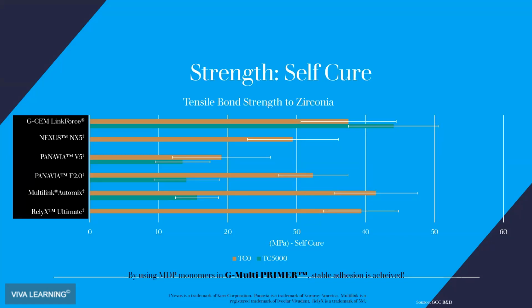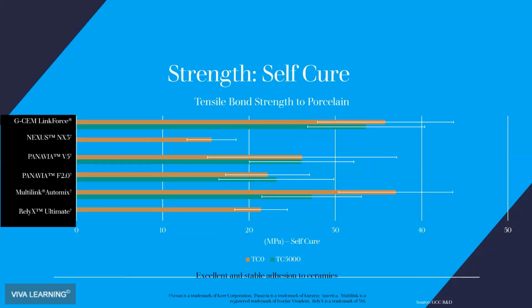We see that when we compare this to the resin modified glass ionomers, which were around 15 to 20, we're now up in the range of 40 megapascals when we start looking at some of these different types of cements, like the G-CEM LinkForce and the RelyX Ultimate and the Multilink. So we get an excellent adhesion to zirconia. And of course, same thing.